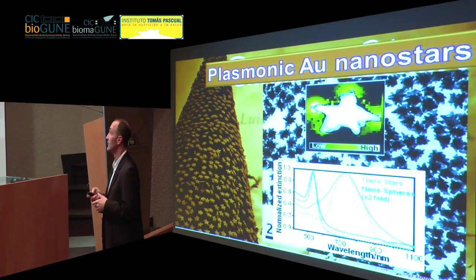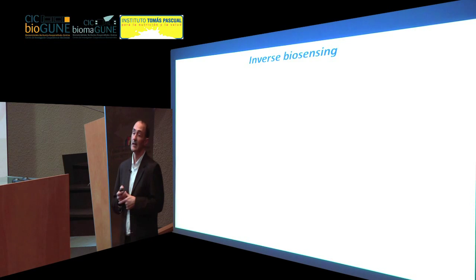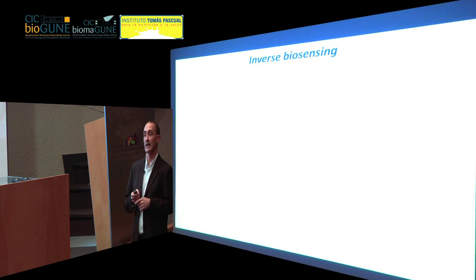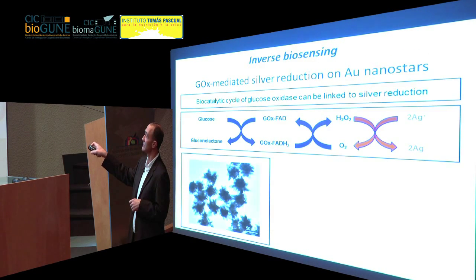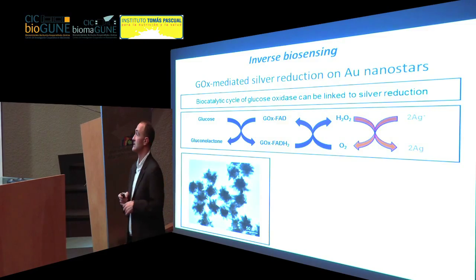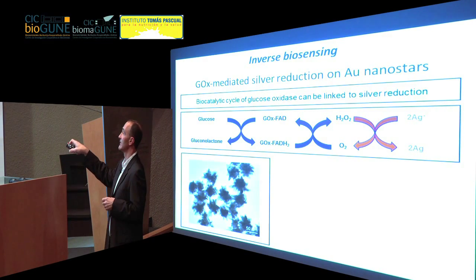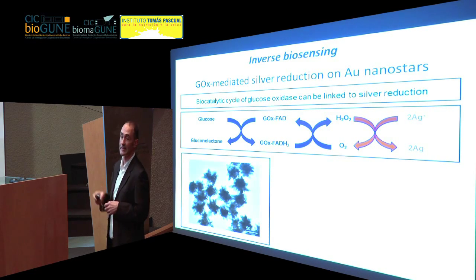So we have done quite a bit of work on exploiting the properties of gold nanostars. I'm going to show you one recent example, introducing the concept of inverse biosensing. This is a collaboration with Molly Stevens at Imperial College. It's based on using a reaction where you use an enzyme to promote the reduction of silver ions in the presence of glucose oxidase. When there is this enzymatic reaction, you promote the formation of hydrogen peroxide, which can get oxidized to oxygen, and then it reduces silver plus to metallic silver.